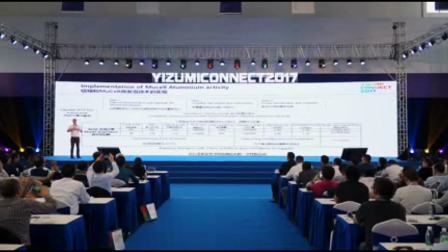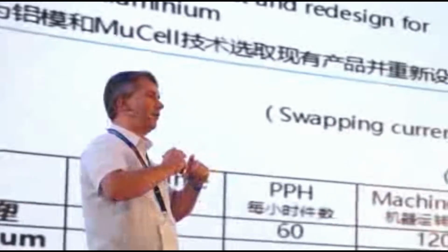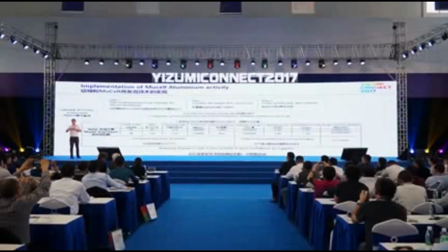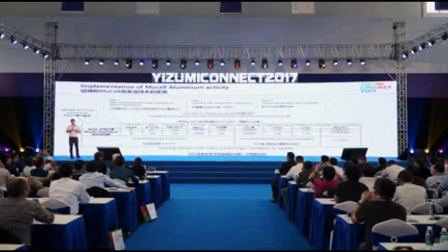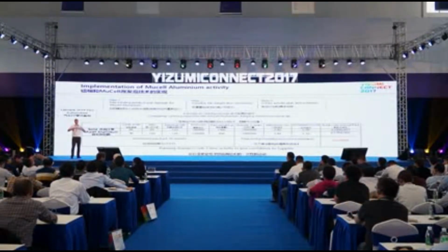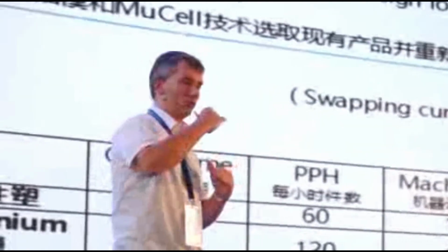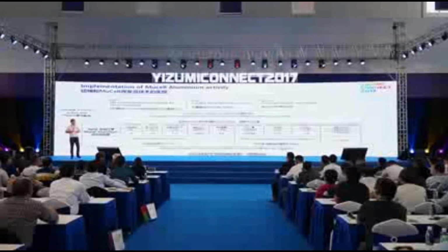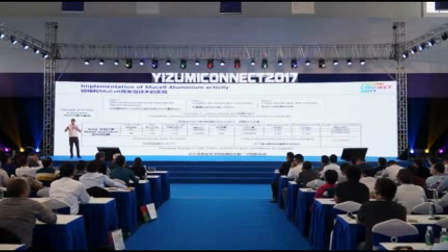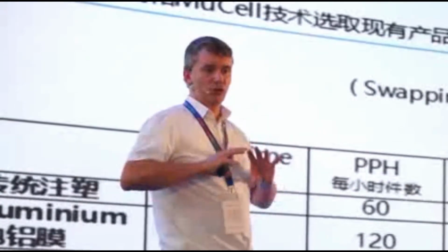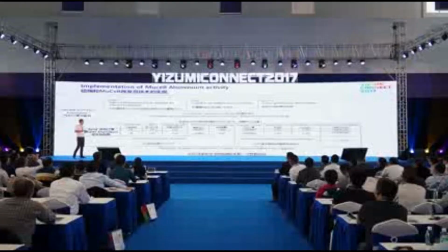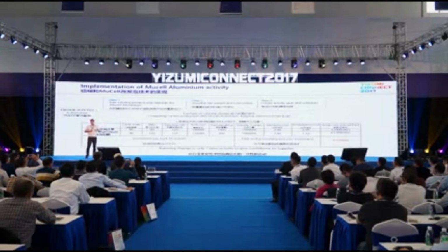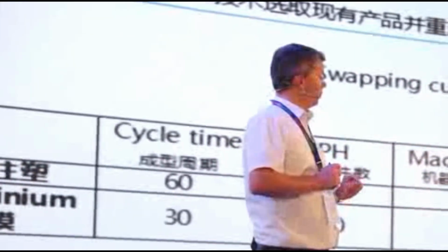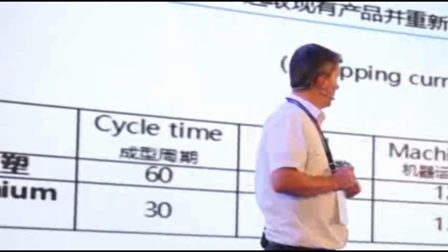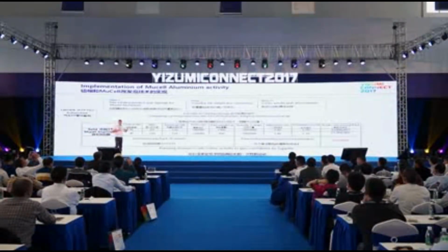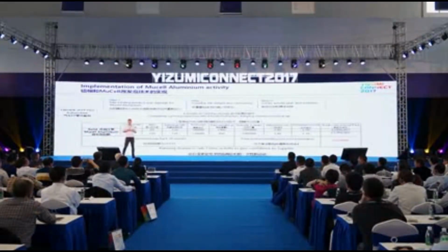The machine hourly rate is only between 5 and 8% more because, of course, with foaming technology, there is some investment. The injection molding machine is slightly more expensive because we have a special screw and you need to buy the gas unit. But if you amortize the cost properly, it shouldn't be a factor to stop investing in this technology. The tool cost in steel was 180,000 euros. In aluminium, we made it for 150,000 euros. So we had a volume of 1 million parts in total, spread over 5 years.